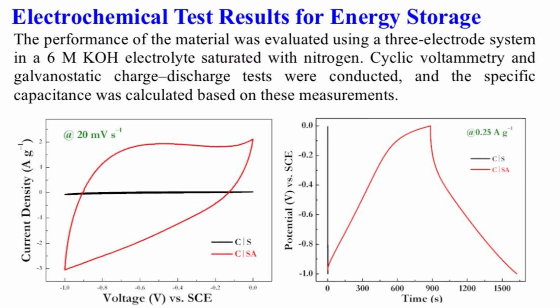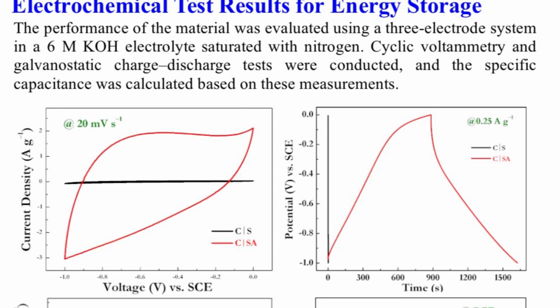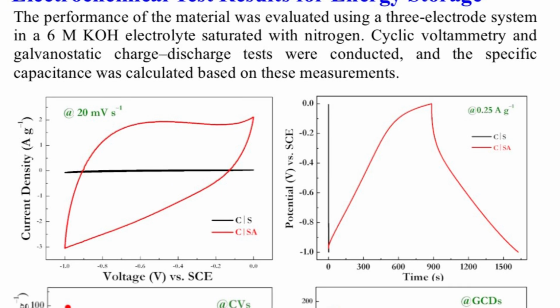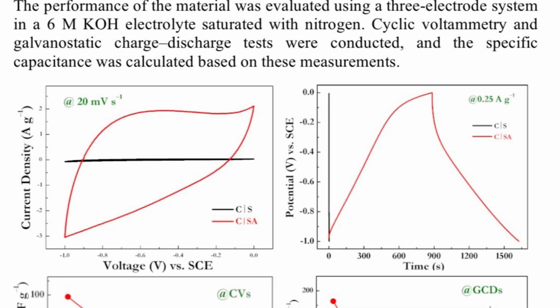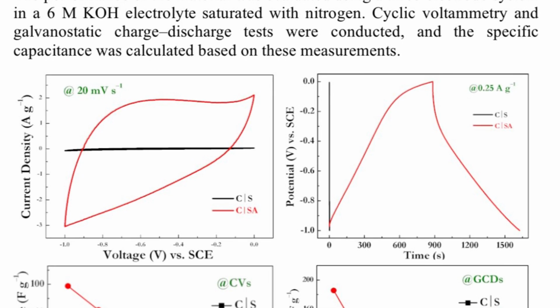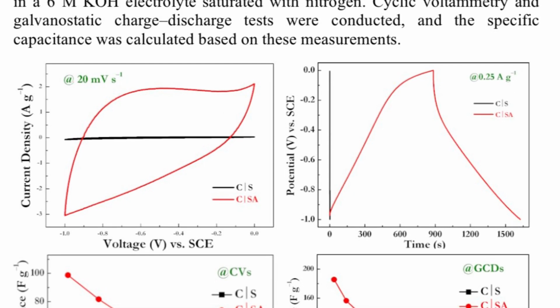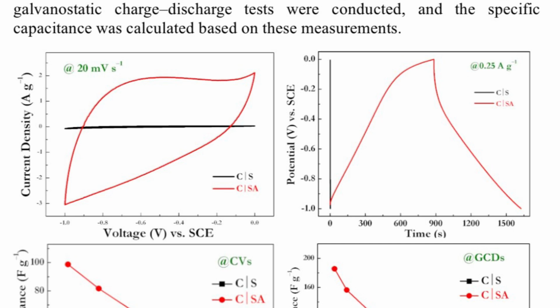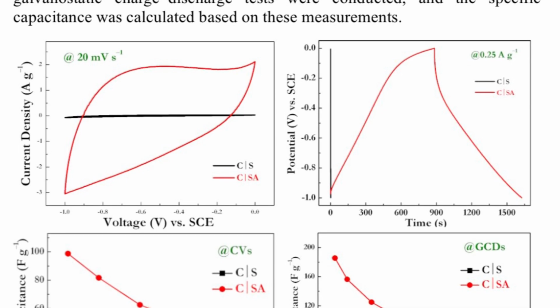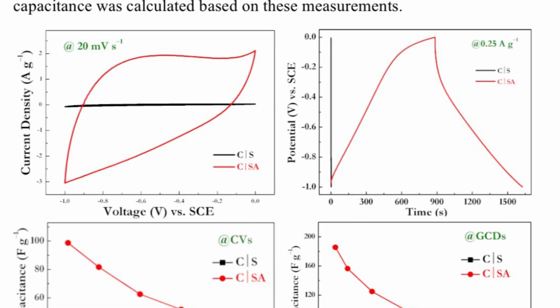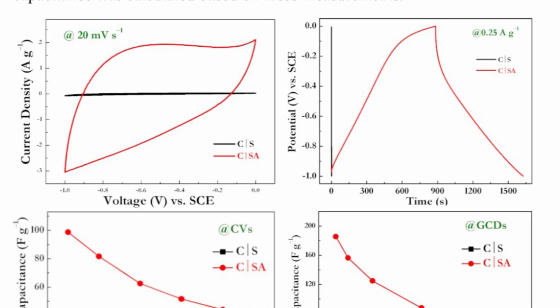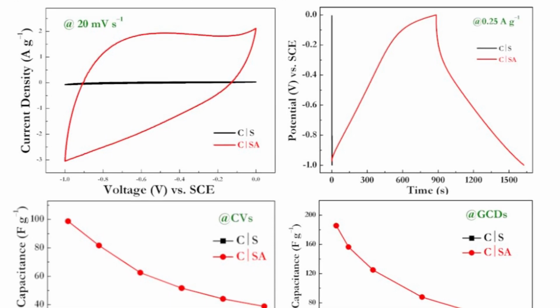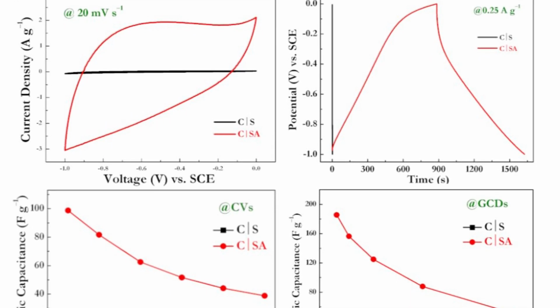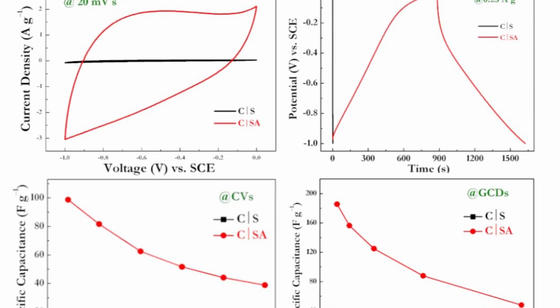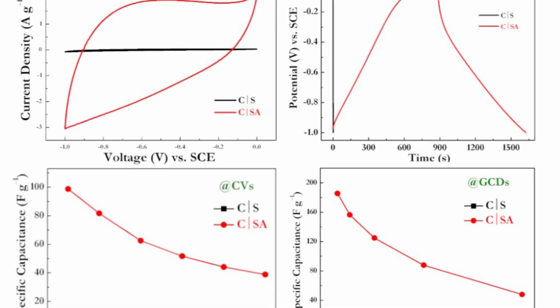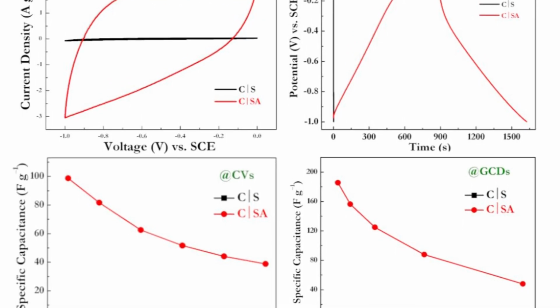Electrochemical results for activated carbon derived from sargassum for energy storage were obtained using a 3-electrode system to carry out electrochemical measurements of the not activated and activated carbon materials in 6 molar KOH. For estimating the energy storage performance, cyclic voltammetry and galvanostatic charge discharge were recorded in a minus 1 to 0 volt potential window using a platinum counter electrode and a calomel reference electrode.